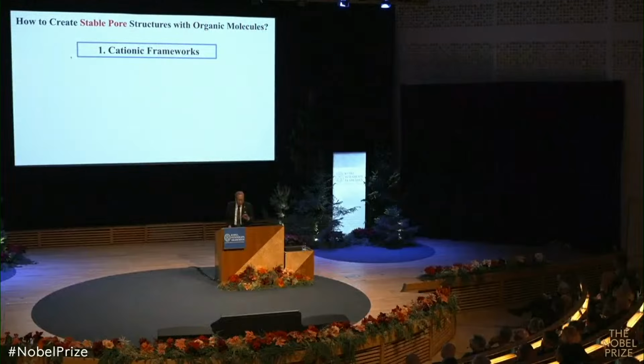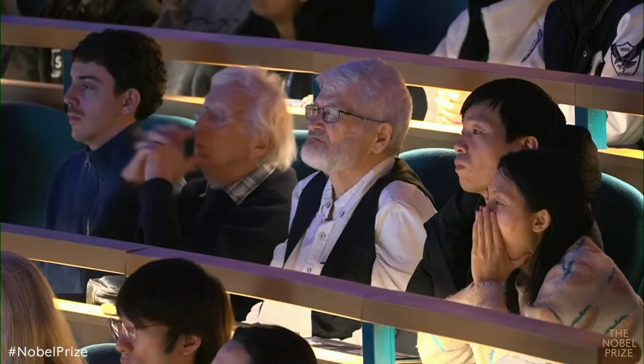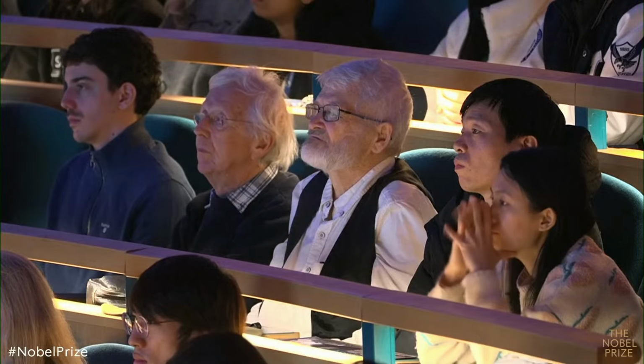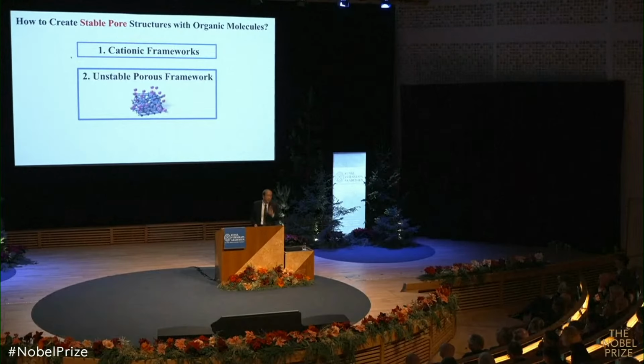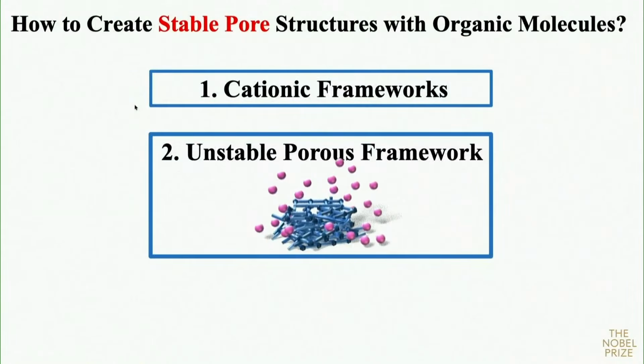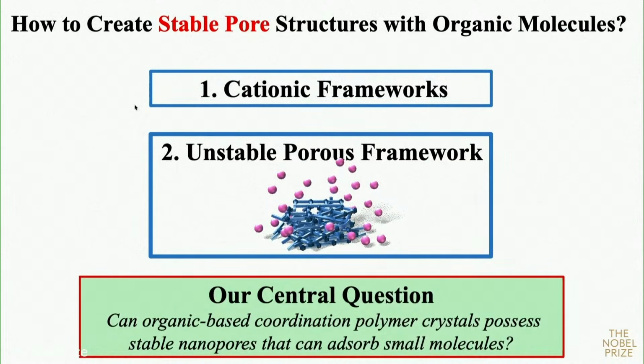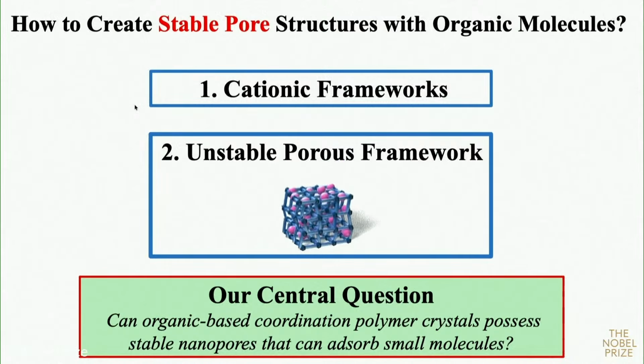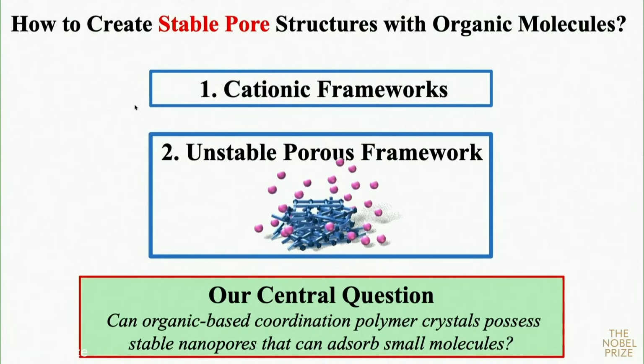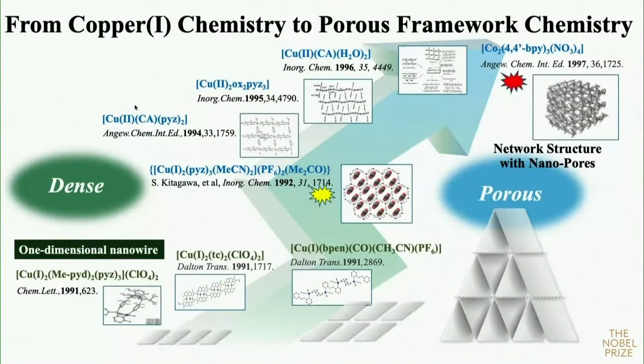However, mostly cationic frameworks had been synthesized so far, so anions were incorporated. Also, the kappa-1 ligand binding energy is not so large, which means it is not a strong bond. So our central question at that time was: can organic-based coordination polymer complex crystals possess stable nanopores that can adsorb small molecules? That's the point.